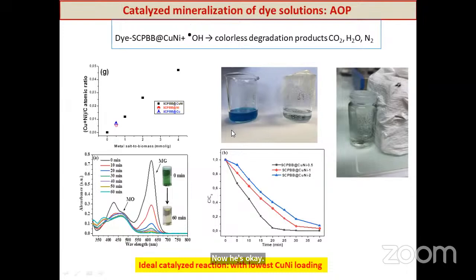What we have tried in the AOP process is to get rid of all organic molecules. Of course, we need additional experiments like HPLC or mass spectrometry or total organic carbon experiments to determine if all organics have been removed, completely transformed into carbon dioxide, water, and dinitrogen, if the initial molecule contains nitrogen. We worked, of course, on single dye solution, but soon we tested the mixture of dyes and see how they behave vis-a-vis the catalyzed reactions.